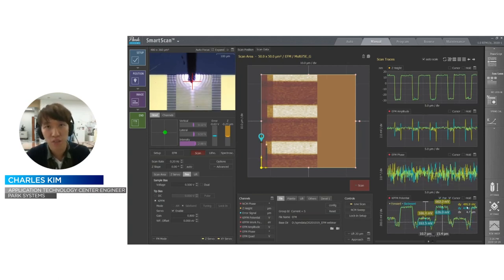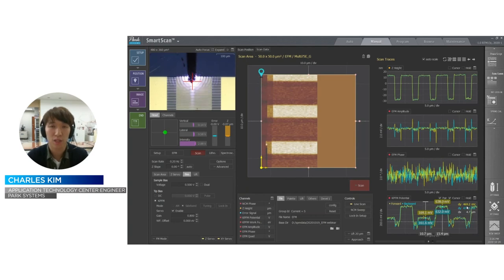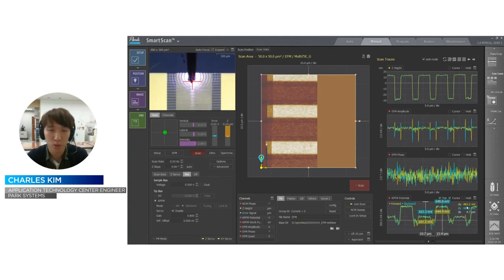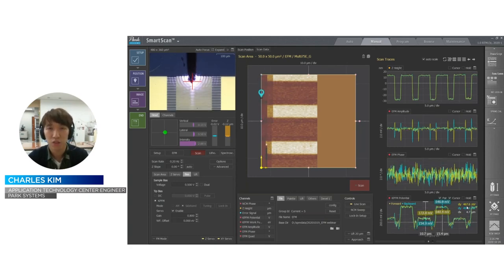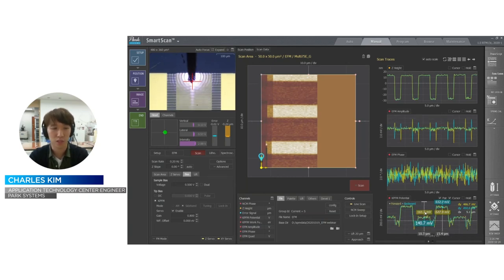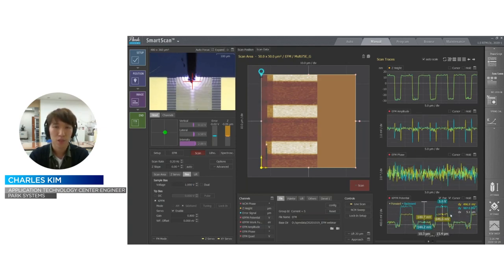Because the sideband KPFM is monitoring the electrostatic force gradient only, and that gradient is only measured at the end of the tip apex, it isn't influenced by the whole cantilever. So it makes possible a much better lateral resolution like this. So if I change to 1 volt of the sample bias, the difference between the grounded and the sample bias applied electrode is almost the same as 1 volt like this.